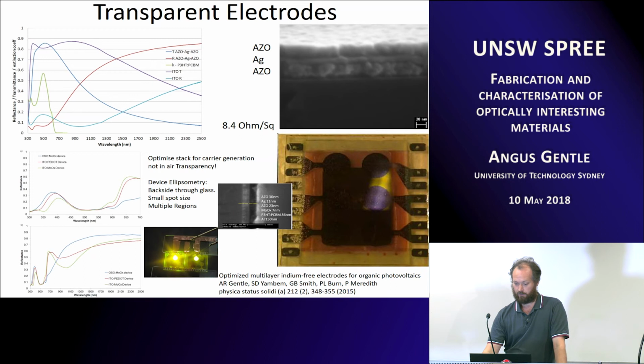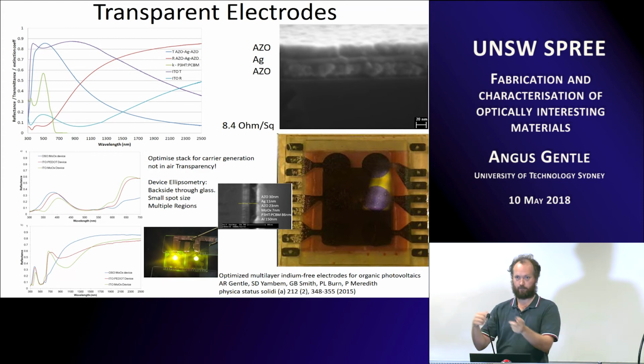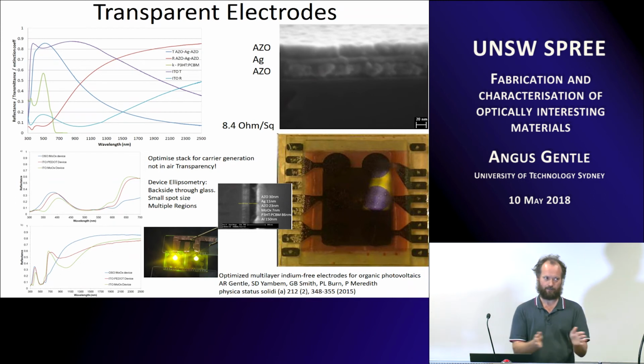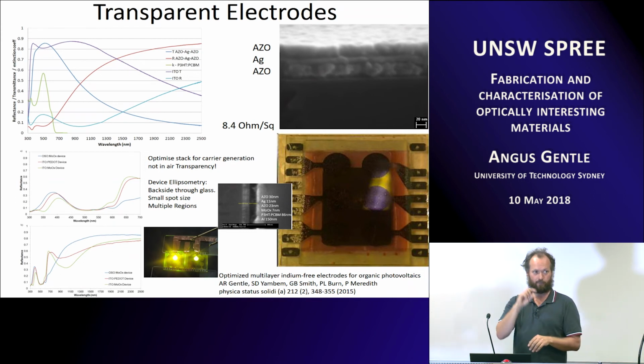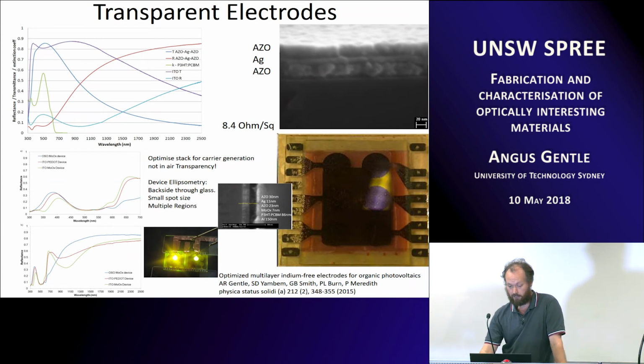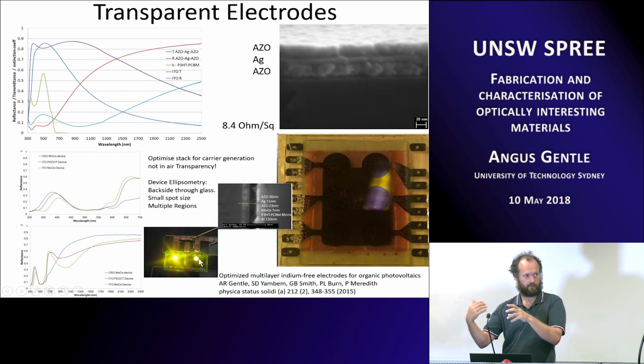In this case we ended up throwing it in one of the SEMs and doing a cross-section on a device, so we could show that what we're getting from the ellipsometry matched the actual device, and then say, look, stop using a Dektak to try and measure the thickness of a polymer, it's a waste of time. And so we did PV and some OLEDs. The bright one on this side was using our stack design, and the one on the other side was using a standard ITO contact.